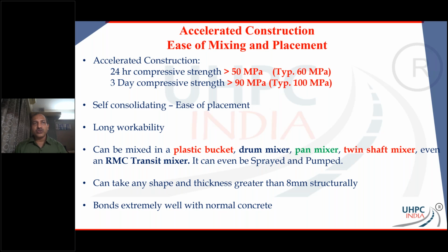You don't have to wait n number of days for curing and then open up the traffic after 21 days. No, no, no. With UHPC, you can do it in 2 days, and you're good to go. UHPC is also self-consolidating. There is ease of placement. You get nice long workability hours that you can work with.